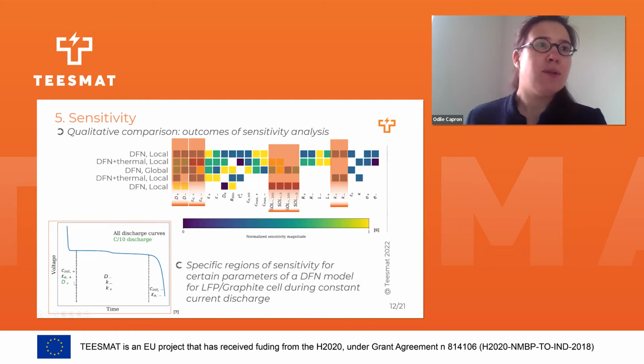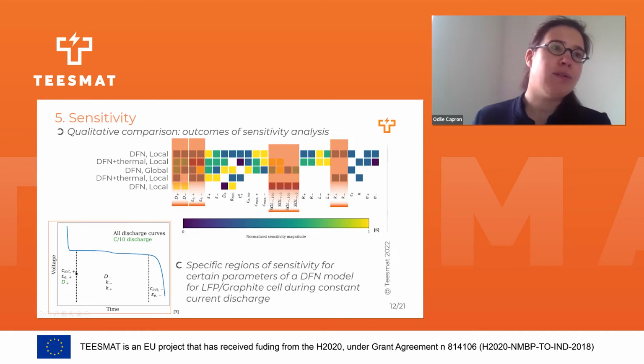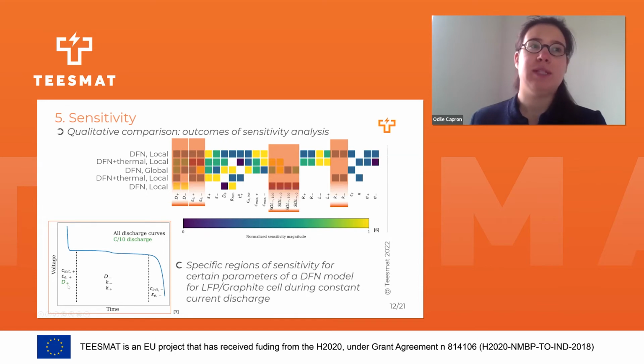And what are the parameters that will influence my curve, my simulation curve? It will be the initial concentration of lithium in the positive electrode, as well as the electrolyte content in my porous electrode at the positive electrode, so the porosity of the positive electrode, and the diffusion coefficient of the positive electrode.